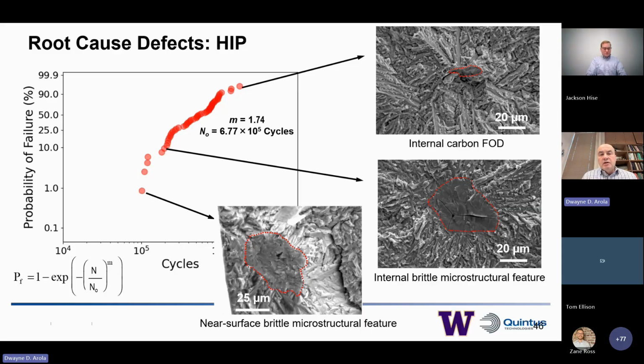So if we pick out again contributions to failure, we see at the low life a near surface brittle type microstructural feature, which I'll elaborate more on in a little bit, and an internal feature, which is relatively similar. And then lastly, up at the high end of life, we see an internal carbon FOD type defect.